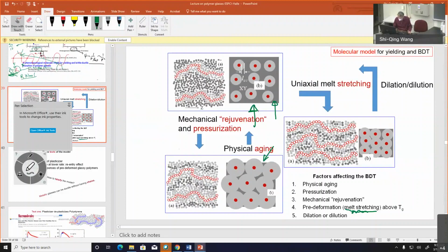And rejuvenation, remember you saw that magician's thing, that you pass through the 2-roll mill, that styrene becomes ductile. Well, that actually rearranged all the monomers. In fact, all the monomers are almost half awake already. So it's very easy to wake them up. In other words, you have changed the energy barrier with the mechanical rejuvenation. So that interprets why this is happening.